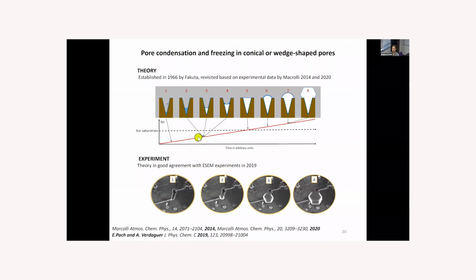When the freezing occurs, the ice starts to grow in the pore until it fills completely. When the ice reaches the surface, it starts to form a conical-shaped cup on top of the pore, which grows until it forms a large enough cup, which allows us to form the ice crystals in their typical hexagonal form. So it is quite amazing that we could visualize this theory by performing the ESEM experiments in 2019.